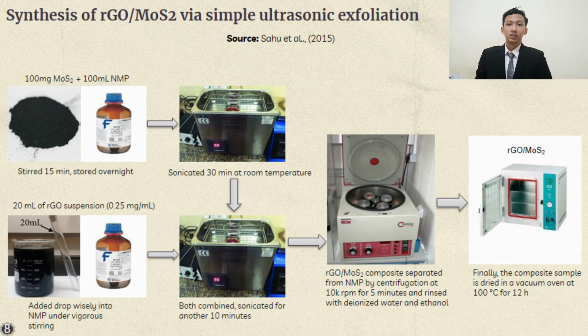Next, the synthesis step of RGO-MoS2 via simple ultrasonic exfoliation. This method starts with 100 mg MoS2 added into 100 ml of NMP. After that, the mixture is stirred for 15 minutes before being stored overnight. Moving on to the next step, the suspension is sonicated for 30 minutes at room temperature.